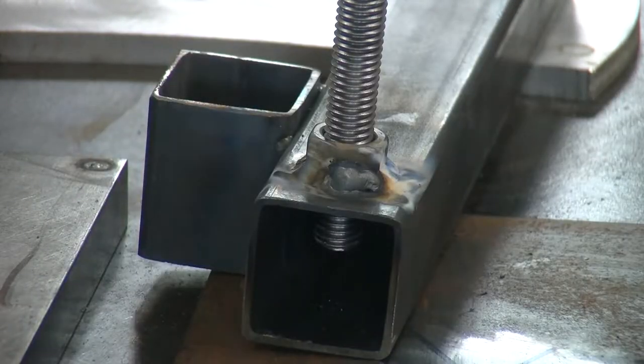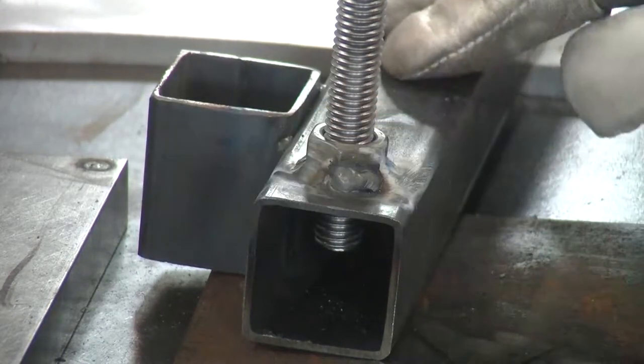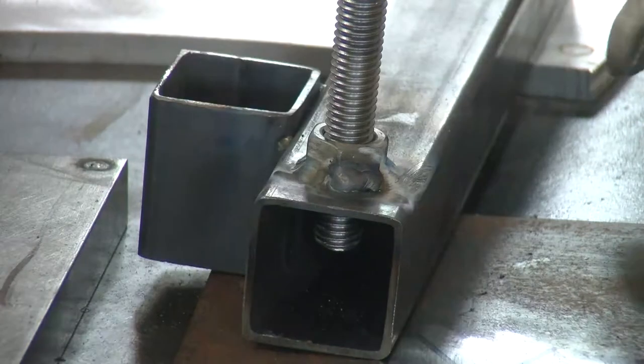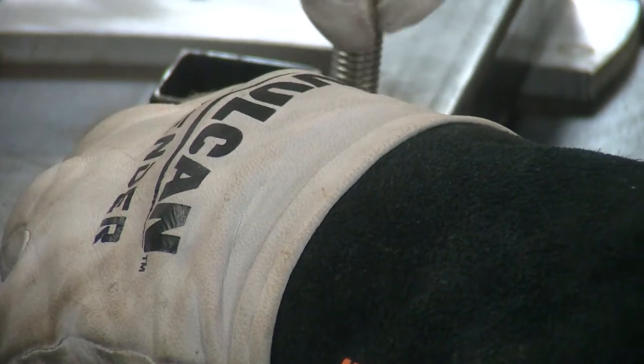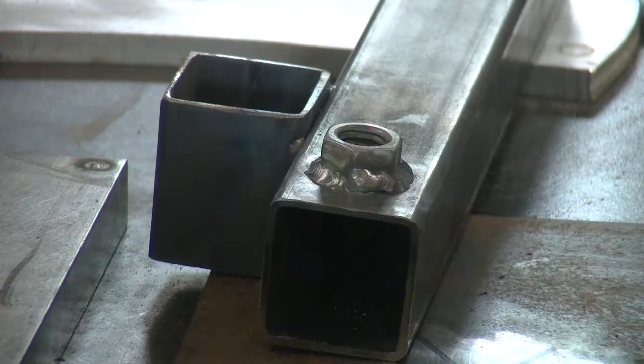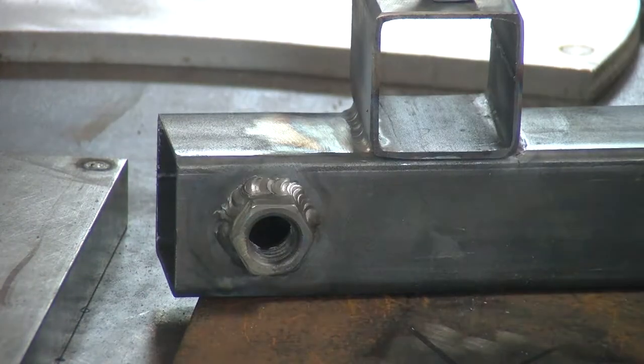I'll be honest with you. I'm just going to leave the rest of that hardware in there probably overnight. See if I can't get more of that galvanized coating off of there, get that schmutz off so it just won't be so gross. You can see how it pops and kind of explodes. That's interesting because that's the first time welding that type of material — welding this galvanized piece of material to just this regular steel pipe. It's not the prettiest thing, but it'll certainly hold. We'll see if we can't get our material a little bit cleaner and do a better job of it tomorrow.